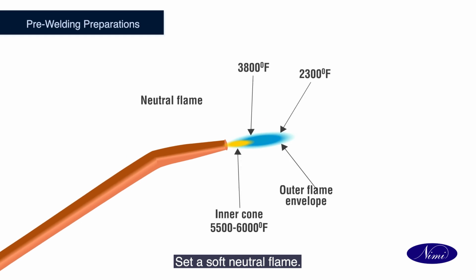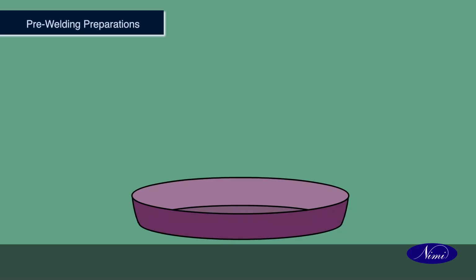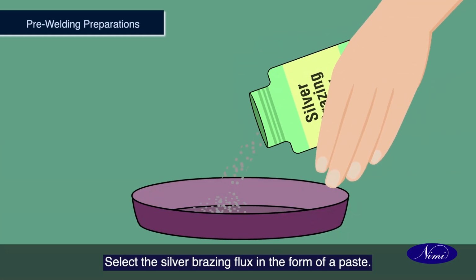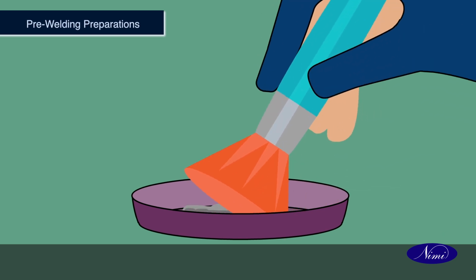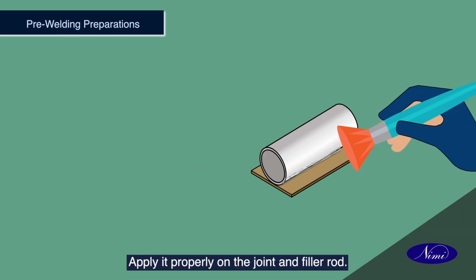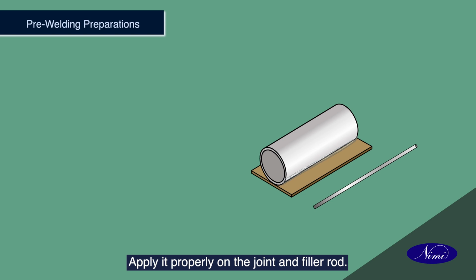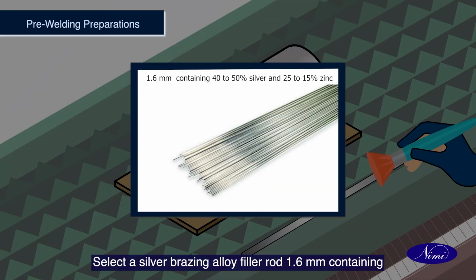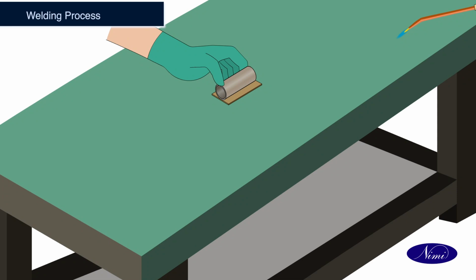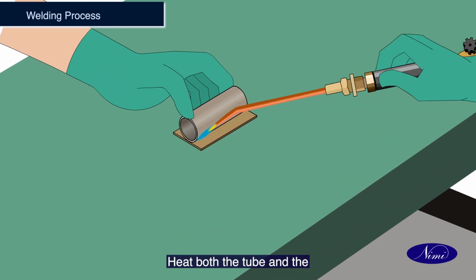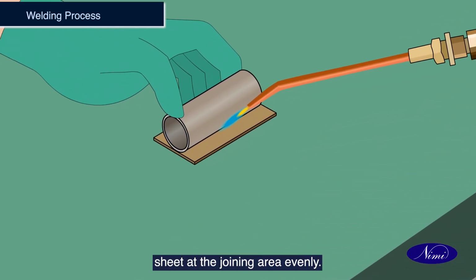Set a soft neutral flame. Select the silver brazing flux in the form of a paste. Apply it properly on the joint and filler rod. Select a silver brazing alloy filler rod 1.6 mm containing 40 to 50% silver and 15 to 25% zinc. Heat both the tube and the sheet at the joining area evenly.